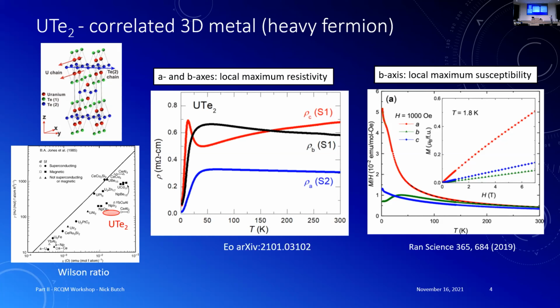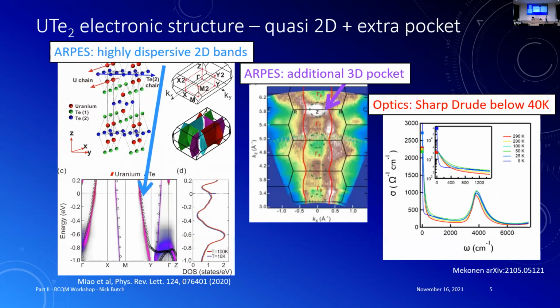Magnetic susceptibility: a is the magnetic easy axis. b is the in-plane direction. So even though the resistivity looks kind of comparable, the susceptibility has a local maximum, and then the c direction looks like a mini version of this. And if we look at the specific heat, it's enhanced. It has a gamma value of about 120 millijoules per mole Kelvin squared. In comparison to some of the other heavy fermion systems, it lives in that same ballpark.